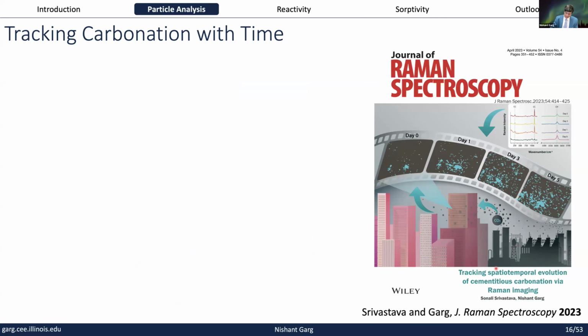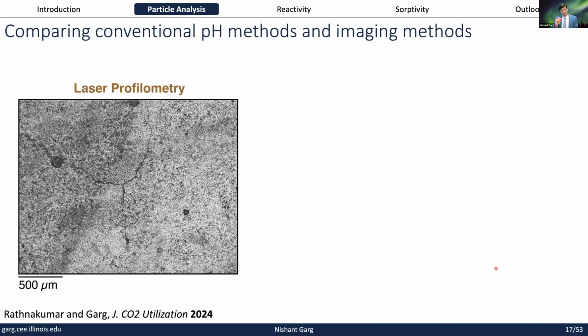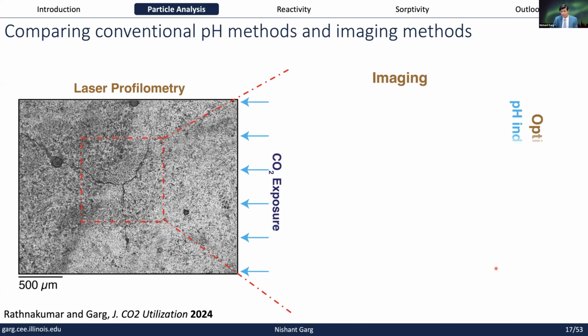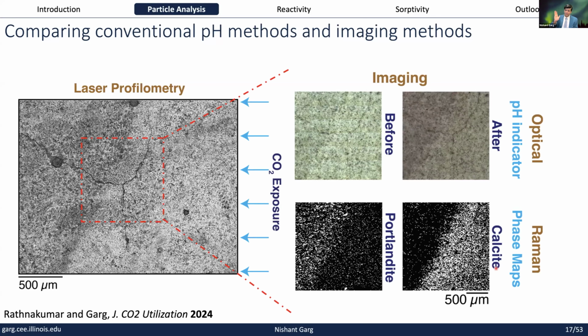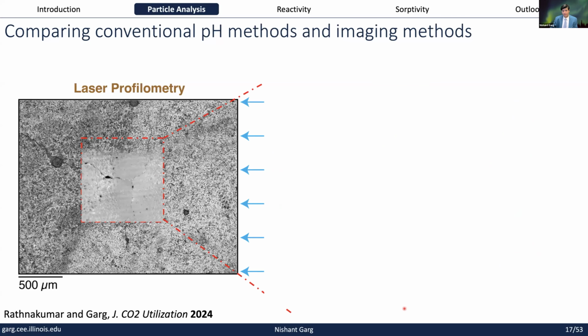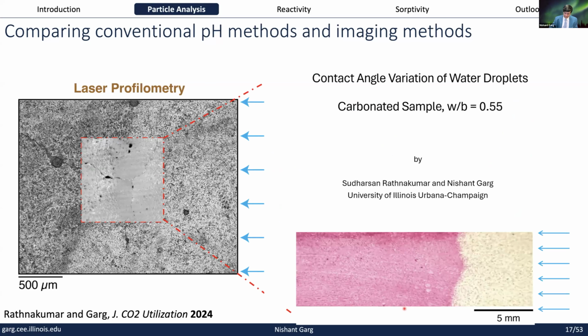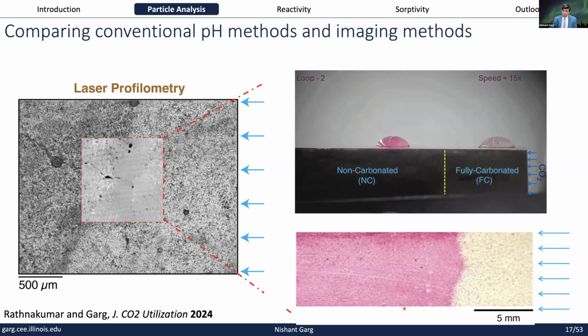But then as a follow-up to this, what we also started looking at is, can we look a little bit deeper into what is happening when this carbonation front is forming? So this work I did with another student, following that early work, we again combined multiple techniques. We take laser profilometry, we expose the sample to CO2 from the right side, and if you image, you have a clear delineation between the calcite front and the Portland front. But then what we really want to know is what is happening at this area which is carbonated. And there, what was very interesting, this work was done by my student Sudarshan, if you look at this droplet test where we measure the contact angle variation, and if you place that droplet on the right side versus the left side, we actually see quite a bit of difference.